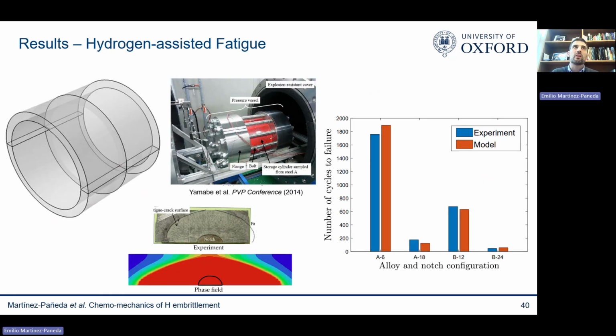And we recently used this to predict the behavior of full-scale components. So this is a pressure vessel, and you can see here how the crack is growing in the pressure vessel. They had done full-scale experiments for pressure vessels with two different materials and notch configurations, and you can see the number of cycles to failure of our 3D simulations agrees quite well with the experiment.